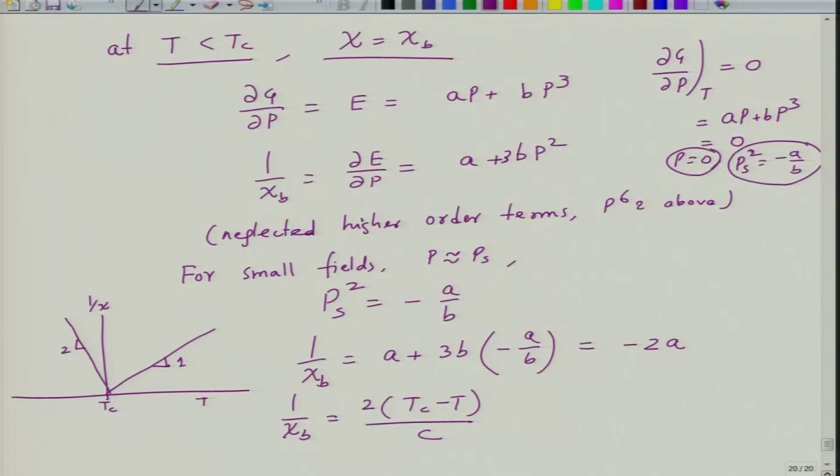We can do a simple analysis of the susceptibility for first order transition as well, which we will do in the next lecture. So, what basically we have seen is the difference between the first and second order transition, the qualitative analysis of first order phase transition as to how the free energy versus polarization varies across temperature, and we see that the subsidiary minima at P is equal to 0 between Tc and T0, and this is basically reminiscent of coexistence of polarized phase with the unpolarized phase, because the two minima belong to polarized phase which are non-zero. The minima that is at P is equal to 0 belongs to an unpolarized phase, and they do coexist together.